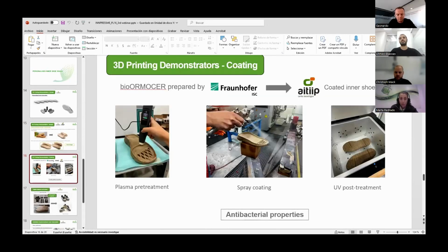This demonstrator was also coated with the bioORMOCER prepared by Fraunhofer. In order for the coating to give the antibacterial properties and to attach properly to this sole, it was necessary to follow the steps that you can see in the picture, which was to apply a pretreatment of plasma. Then we spray coated following the directions provided by Fraunhofer, and then it needed that UV post-treatment to fix the coating and to let it dry and cure.